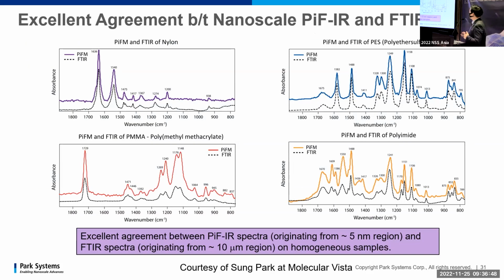So this is the PIFM and FTIR data of nylon, PES, polyimide, and PMMA. You can see they correlate very well. The reason it correlates so well is that in FTIR, these materials are really homogeneous. If they have some other materials mixed in, then the FTIR signal becomes really noisier.